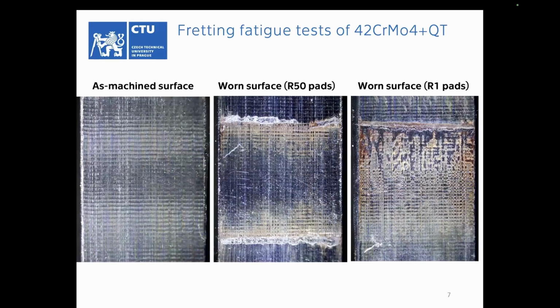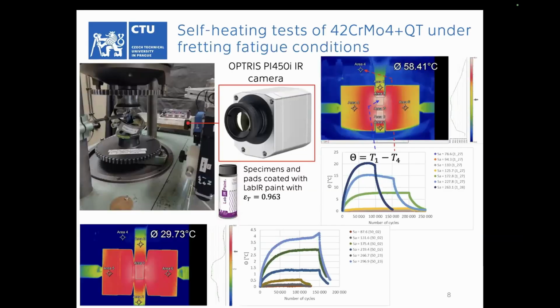Just for information, here is the initial surface. These are photos of the surface damage after the test termination for the single surface pads, and for the bridge pads, illustrating a big difference, let's say, not only in damage but in contact surfaces, in contact slips, sorry.